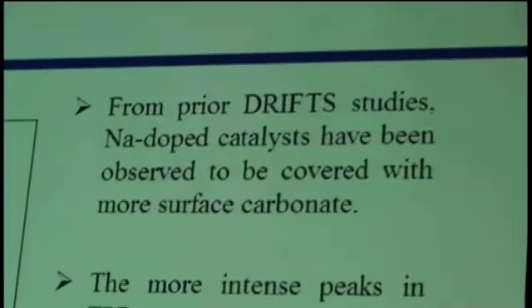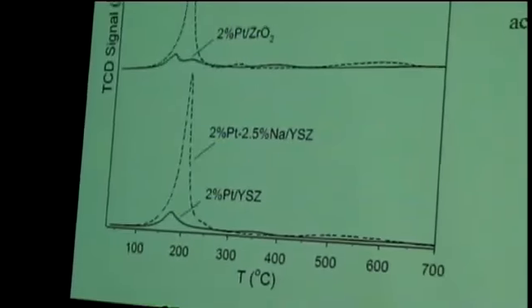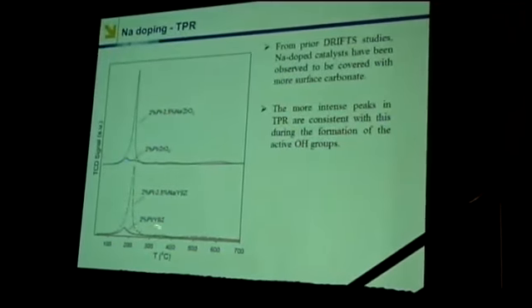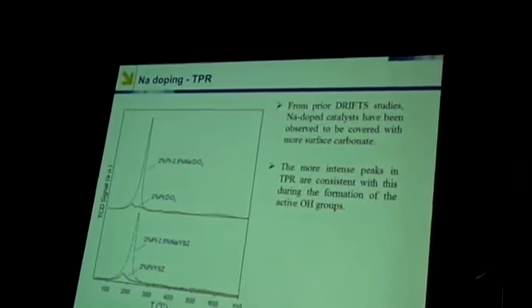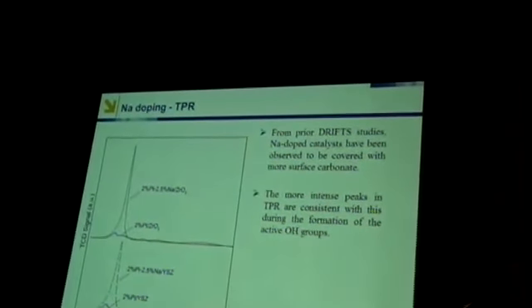By putting sodium on the catalyst, initially the catalyst will have more carbonates. We observed that in DRIFTS spectroscopy. That's probably why we see these more intense peaks during hydrogen TPR for the sodium catalyst relative to the undoped. Here when I say undoped, I mean without sodium.